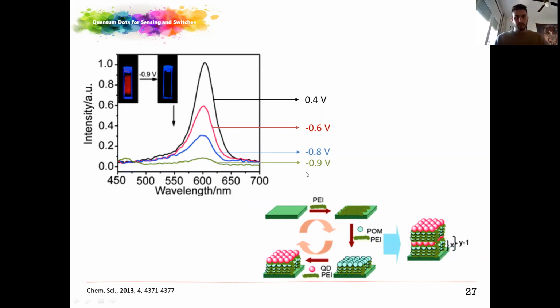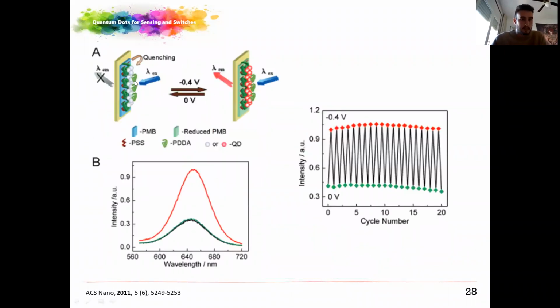There is no electron transfer here between the quantum dot and the polymer, but it's a very interesting way to see a switch. Here in this case, there is electron transfer from the quantum dot to the polymer. Here there is a polymer with a quantum dot, and after the application of a higher potential, the polymer is oxidized. There is an electron transfer from the quantum dot to the oxidized polymer, and after the reduction, this electron transfer disappears. So we can recover the fluorescence, resulting in a switch.